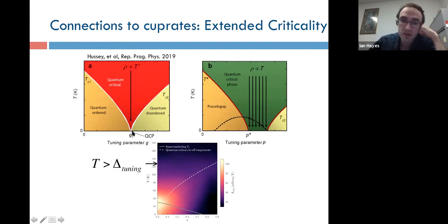The pnictides up until now have seemed more conventional critical systems in the sense that things are concentrated really near a point where the antiferromagnetic order ends. I think one takeaway of this observation is that there is more of a connection between these 2 scenarios than originally seemed to be. So you can see pretty clearly there's some region where it looks like temperature is exceeding some detuning energy and you're getting uniform behavior.